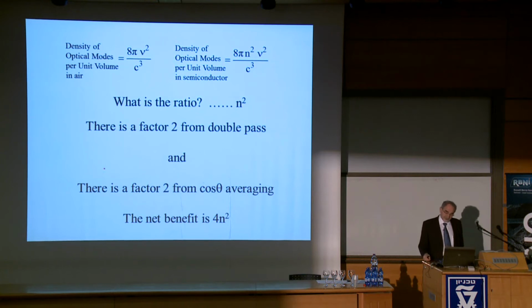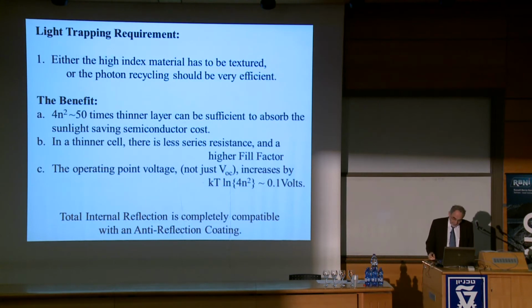So I mentioned the factor 4n squared. Where does it come from? Well, the mode density, if you think in statistical mechanics, there's a refractive index squared in the mode density. Then there's a factor of 2 because the light ray bounces back and forth, and there's a more subtle factor of 2 because the light ray is bouncing at an angle, so you get an increased path length. And after everything is worked out, it's 4n squared. Now, this is a quite significant benefit. Obviously, it means you can make the semiconductor very, very thin, and the semiconductors cost money. So if you use less semiconductor, you can bring down the cost.